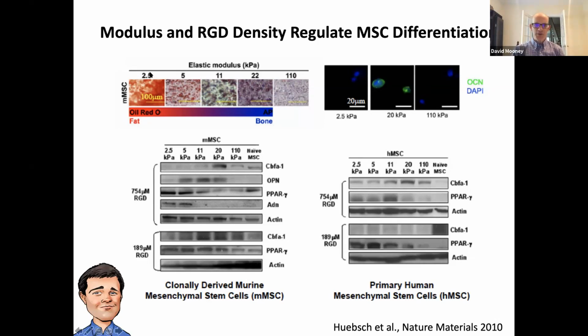So if we focus on the upper left, you can see that when the cells are put in a pretty soft gel, basically we got this red staining, which indicates that these cells are becoming fat cells or adipocytes. When you put the cells into this intermediate stiffness gel, we see this blue staining, which indicates that the cells are becoming bone-forming cells. And when they're in really stiff gels, they actually didn't differentiate down any pathway. And the rest of this data is just some molecular characterization of this transition and a demonstration that the density of the adhesion ligands can also play an important role in interplay with the mechanics.